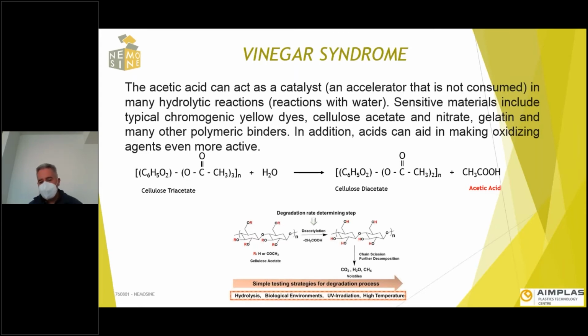Here we can see a very summarized mechanism of this reaction, for example with cellulose triacetate. In the presence of water or humidity, we suffer this vinegar syndrome. We produce acetic acid and a break of the cellulose acetate molecule into monomers, cellulose diacetate. If we have long cellulose acetate polymers suffering this process continuously with time, we produce acetic acid that catalyzes the reaction and accelerates it. Each time we are cutting the polymer into smaller pieces, oligomers or polymers. And finally we will see in our movies a complete deterioration of the material.